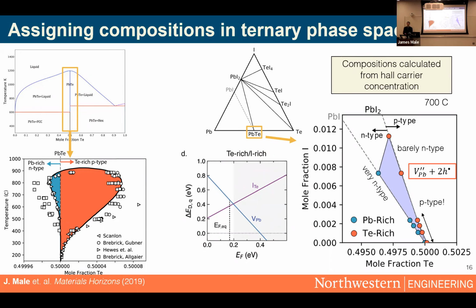And you can model how much the band structure affects your carrier concentrations. However, if you're starting with Hall carrier concentrations and everyone's using them, it's a pretty good indication of phase widths. So no, it's not perfect, but in my mind, it's the easiest and best way to get at this. It's standard. Essentially, that's where this phase diagram actually comes from, Hall carrier concentration measurements. So you can't measure this in an SEM. It's like impossible. So you have to turn to the charge carriers.